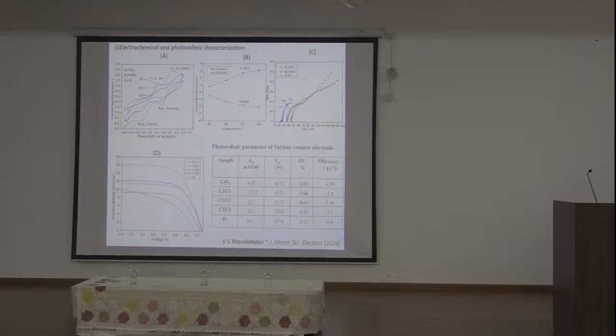And also the redox potential is a major concern in this DSSC application because there is fast dye regeneration. It depends on how fast the electrolyte is getting reduced at this counter electrode, then only fast dye regeneration improves the overall performance. Then at different scan rates, we see how the oxidation and reduction potential is changing. Here we can see the linear relationship with increasing scan rate.